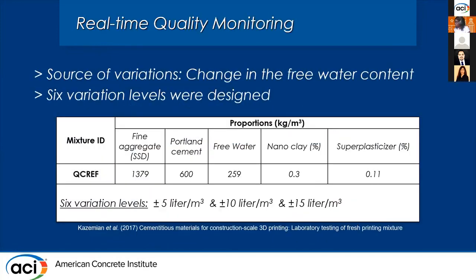In terms of material variations, I think one of the most common issues is the variations that we have in the free water of the printing material. In conventional construction, we also have this problem because the accurate measurement of the moisture content in the aggregates, especially sand, is not really easy. So based on that, I selected that as the source of variation, and then I designed 6 levels of variations that you can see in the table.